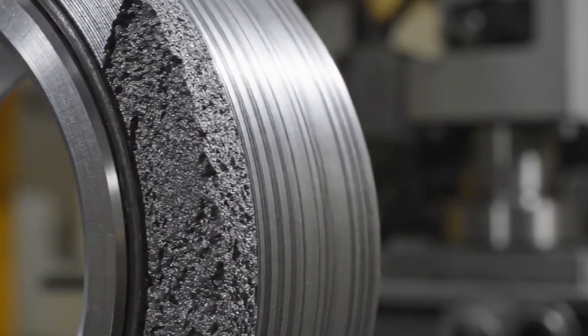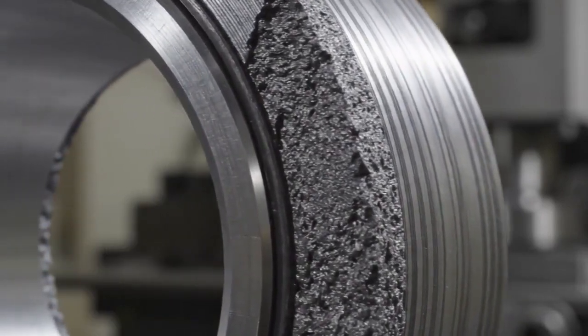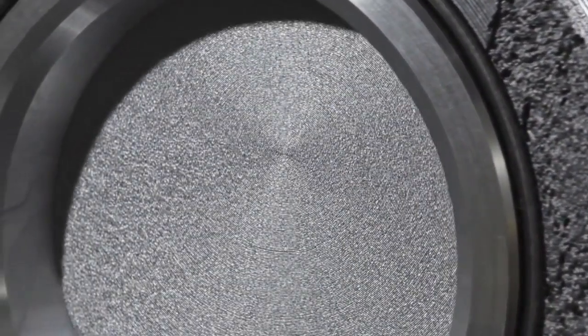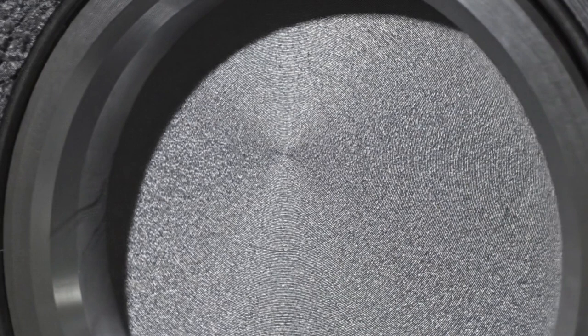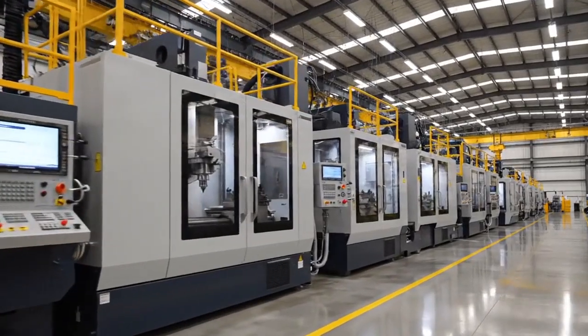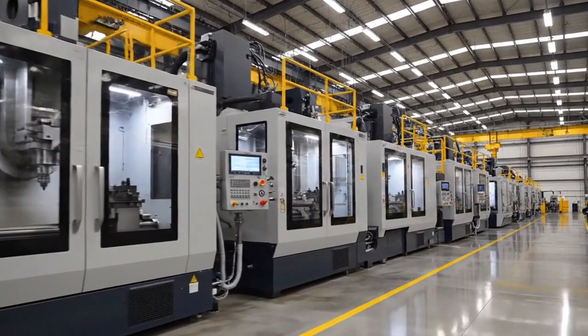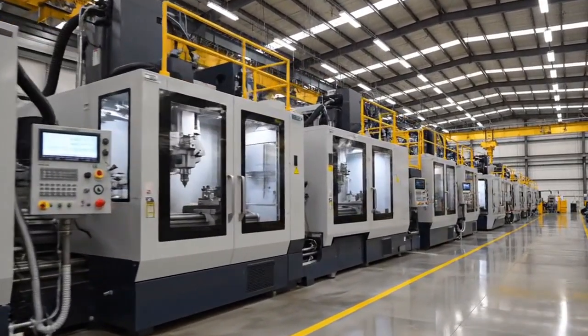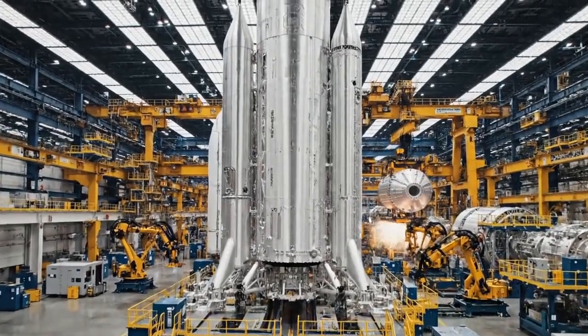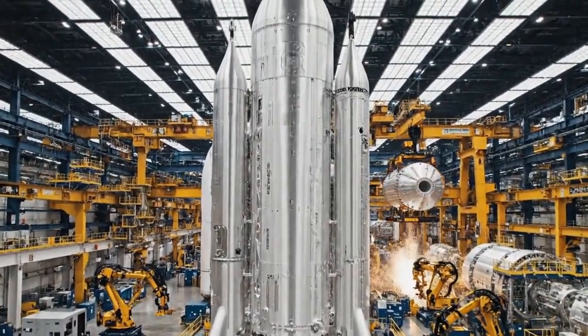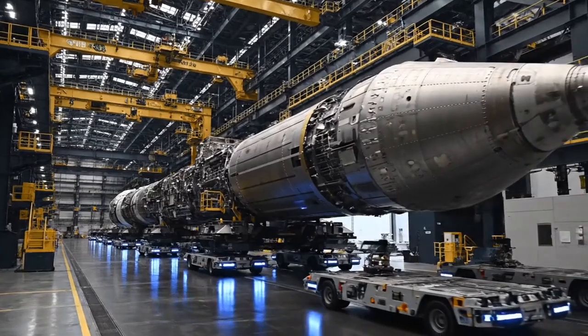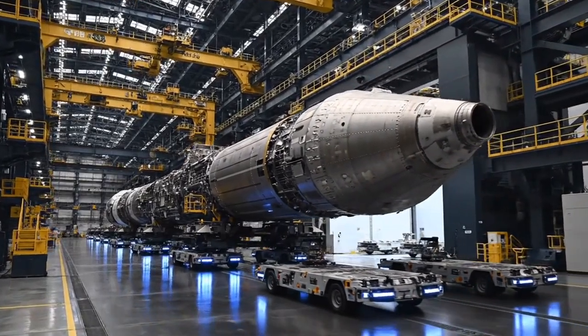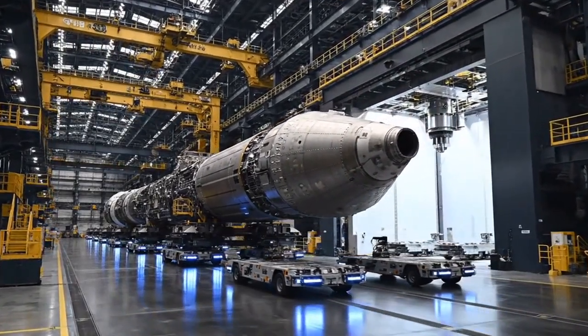While the 3D printing process achieves near-net shape geometry, the critical interface points, such as the mating rings for the orbital payload fairing or the reinforced thrust puck where the main engines attach, require absolutely, mathematically perfect flatness to ensure pressure seals. Therefore, the same facility houses enormous vertical turning lathes and multi-axis CNC milling centers. The entire printed stage, standing as tall as a 10-story building and weighing several tons, is horizontally transferred via autonomous guided vehicles into the subtractive machining cell.